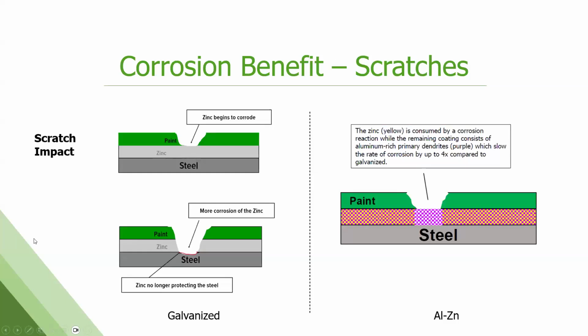So a little bit to illustrate what's happening and why its corrosion is so good. And I need to use AI maybe to come up with some better graphics than this at some point. But on the left, traditional galvanized: base steel, zinc layer, paint on top. If you scratch through that paint, which happens over time or during installation, and that zinc coating is exposed, it's going to start weathering away. Now that's going to take a few years. It doesn't happen instantaneously, but once that zinc coating is gone, you're now down to base steel.